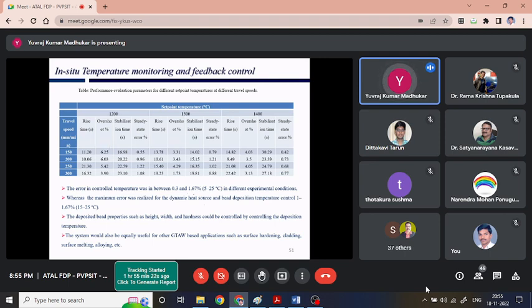So typically, the error in this developed system is of the order of hardly 0.3 to 1.67%, which leads to 5 to 25 degrees centigrade only. And in case of a dynamic heat source, it goes hardly from 1 to 1.67%, which in terms of temperature is hardly in the range of 15 to 25 degrees centigrade. Now if we talk about the melting point of this steel, it is very close to 1450 degrees centigrade. Considering that 1450 degrees centigrade, the error in this temperature range is very much lesser.